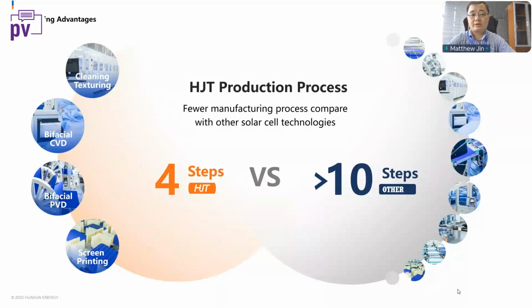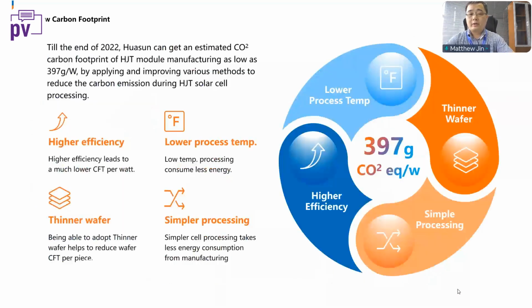For the processing advantage, compared with the regular technology, the HJT production process is quite simple, just 4 steps, compared with the other technology, which is more than 10 steps. Based on this, the potential cost reduction will be more competitive compared with the regular technology. For the ultra low carbon footprint, based on the HJT higher efficiency, lower process temperature, thinner wafer and simple processing, by the end of this year, Huasun can get around 397 grams per watt for the HJT module manufacture. This low carbon footprint is a very good value for using the HJT technology and product, in China and also in Europe.